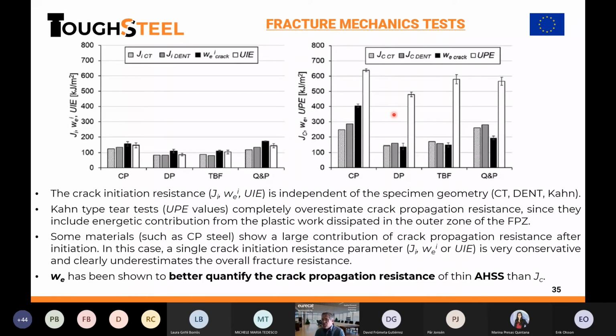So this is the picture that compares initiation and propagation energy. You see that the initiation resistance, when the crack starts to grow, for compact tension, DENT, essential work of fracture, J-integral, or the Kahn tear test, is almost similar, because the crack is just at the beginning. It hardly sees what is ahead of it. So with this, initiation is more or less independent of specimen geometry.